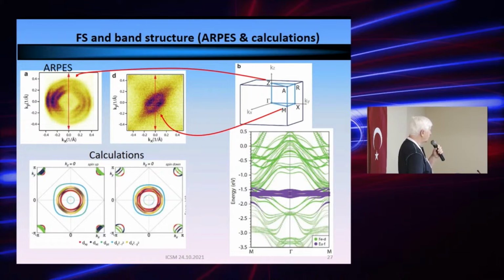Since this is the result of calculations, they can be identified with the europium 4f electrons, whereas those in the vicinity of the Fermi surface are iron 3d electrons. Now clearly, another reason for the decoupling between superconductivity and magnetism is the fact that they are located at a very high energy difference from each other, so that they do not talk with each other, at low temperatures at least.